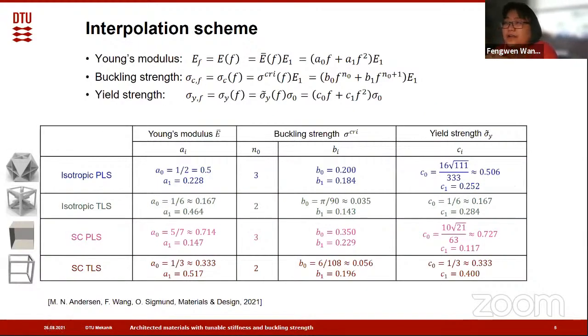My colleague studied these four types of macrostructures for different volume fractions, and we obtained two terms interpolation schemes, both for Young's modulus and buckling strength and yielding strengths. These two terms interpolation schemes can accurately predict Young's modulus, buckling strength, and yielding up to a volume fraction of 50%.